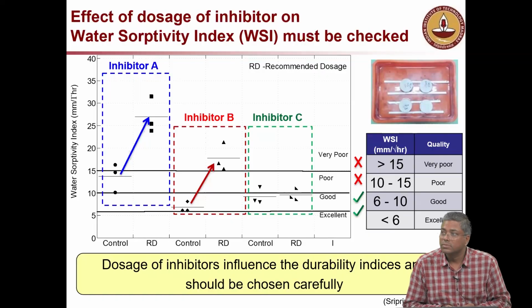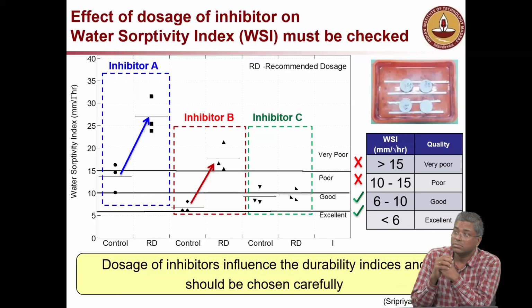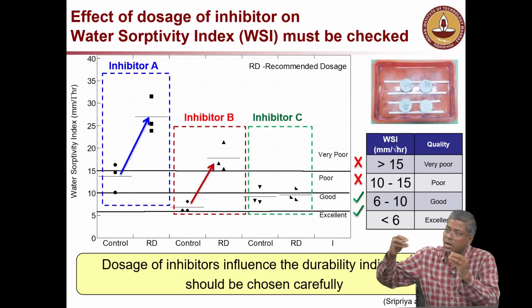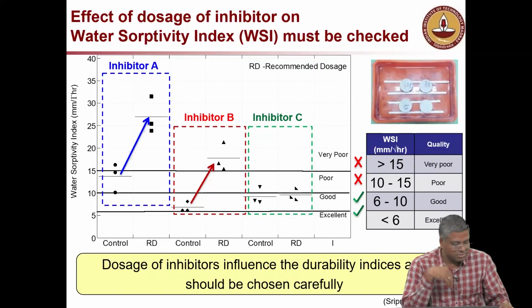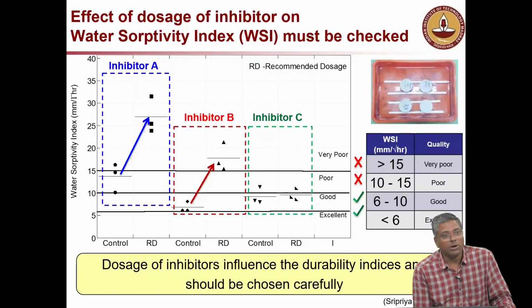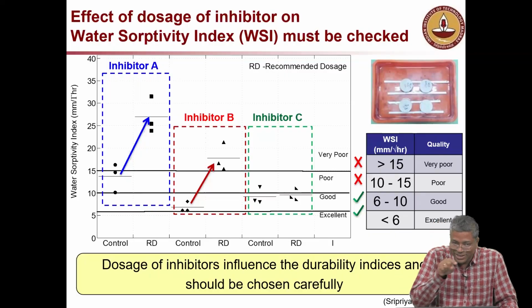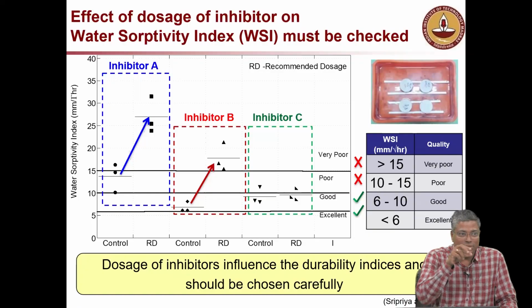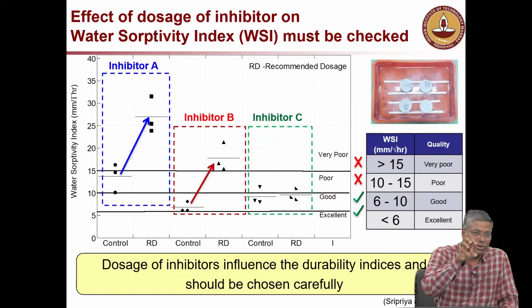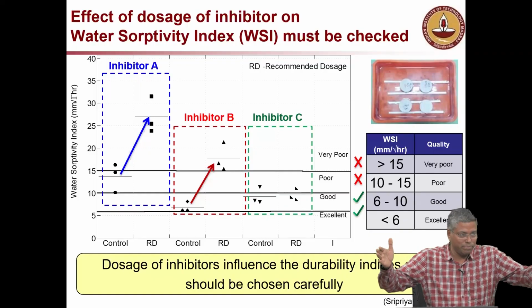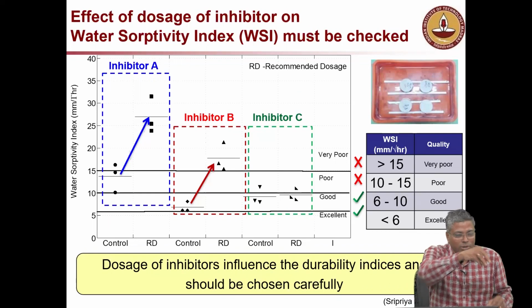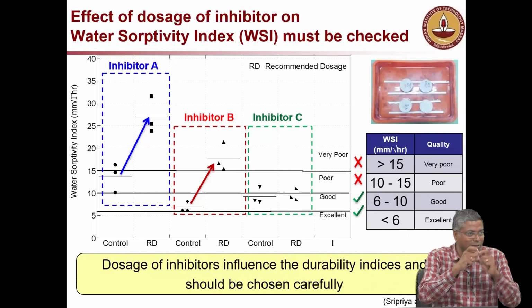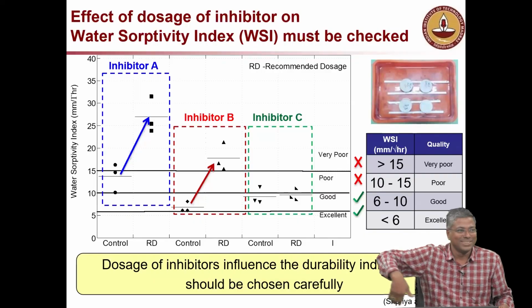Okay. Yes. Only on the steel surface. No, steel surface. The rebar, that is where the passive film, that's a challenge. So this is a very good point, because 90% of the inhibitor is waste. Or even more than 90%. If you look at the volume of inhibitor which is actually working on protecting corrosion, preventing corrosion, it's very, very less. Imagine a metro pier, you have, let's say, 2 meter by 2 meter, and you have whatever reinforcement, you add the area of contact with steel and concrete and the chunk of concrete which is inside. It's all wasted.